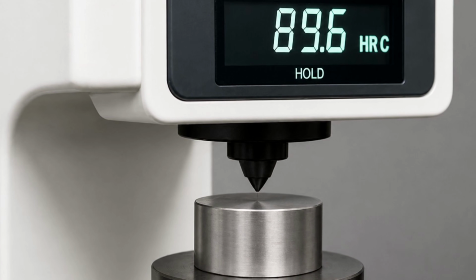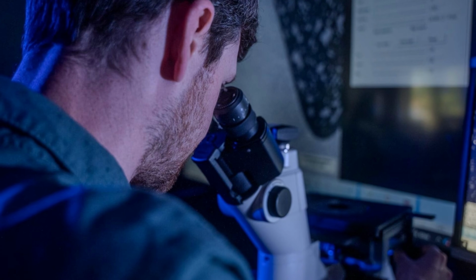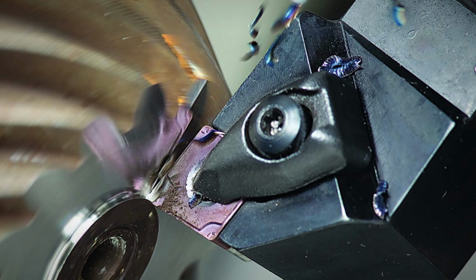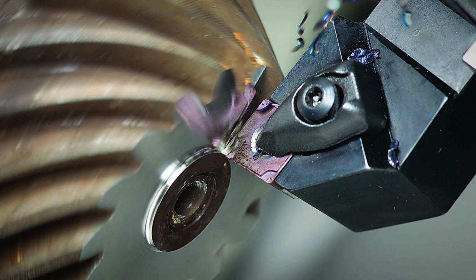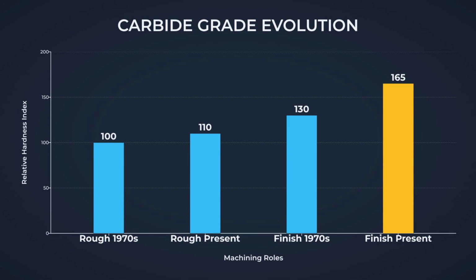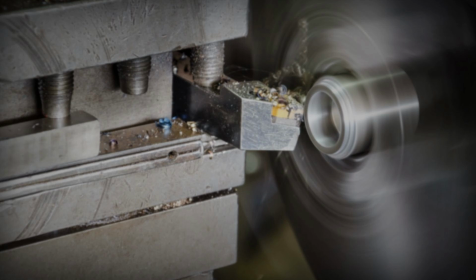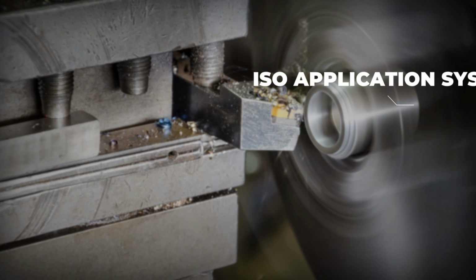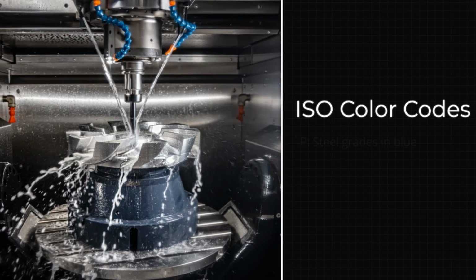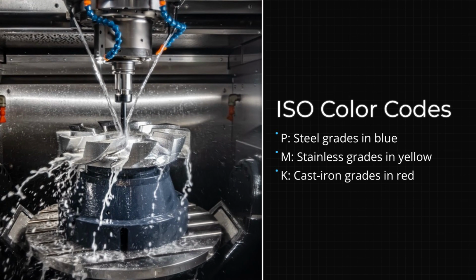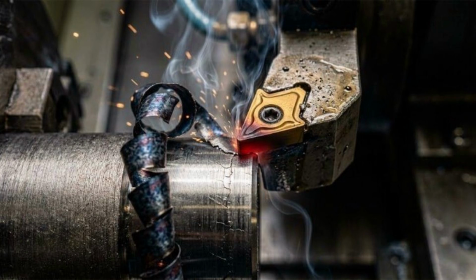Every carbide grade is a trade between two levers: cobalt content and grain size. More cobalt and coarser grains buy toughness. Less cobalt and finer grains buy hardness, from roughing grades carrying 10% binder or more down to finishing grades near 3. The ISO application system sorted the world's workpieces to match: P for steel, coated blue; M for stainless, in yellow; K for cast iron, in red; with N, S, and H added later for non-ferrous metals, superalloys, and hardened steel.